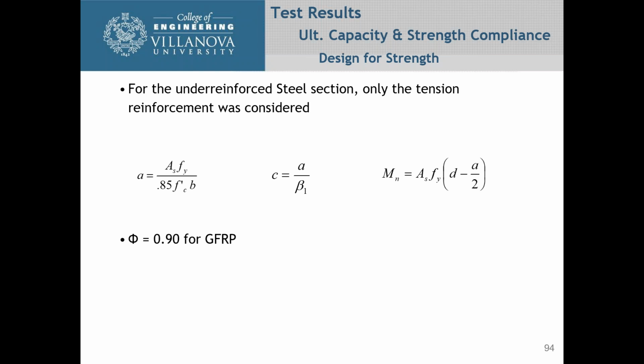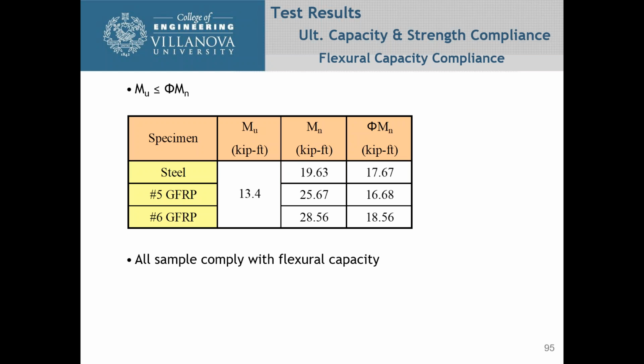For the under-reinforced steel section, only the tension reinforcement was considered. So therefore, your Mn is equal to the area of steel times the yield stress times the sum of d minus a over 2. And for steel, your phi is 0.9. Calculating out for your steel, your phi Mn is 17.67 kip-feet. And for the number 5 bar, it's 16.68, and number 6 bars is 18.56. All of those are greater than the 13.4, so all the samples comply with flexural capacity.